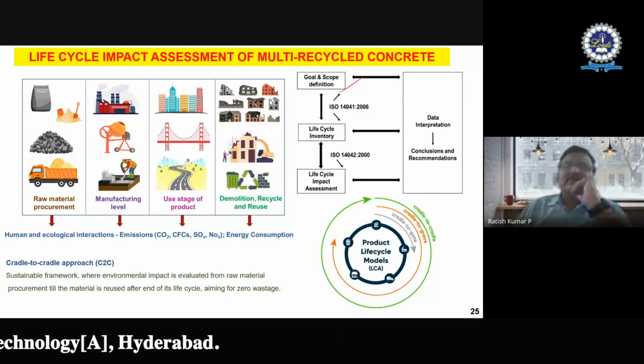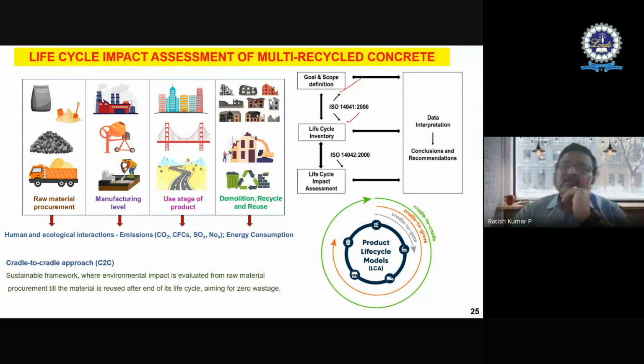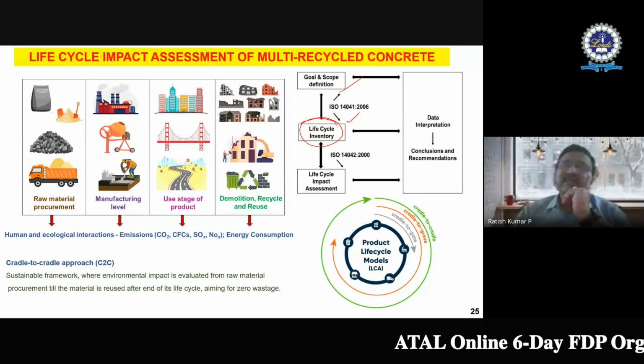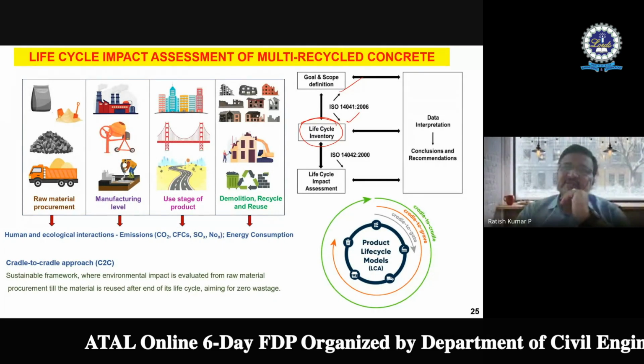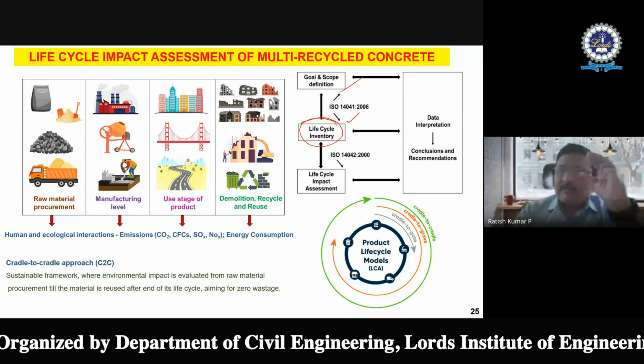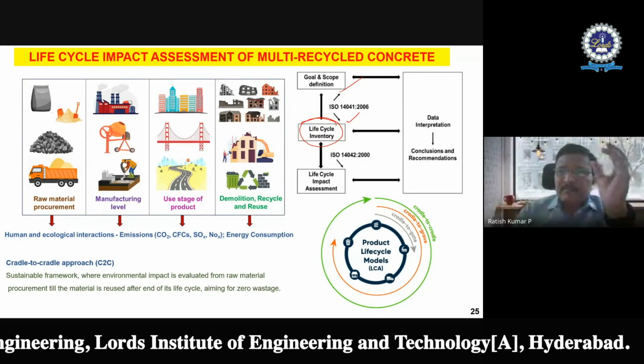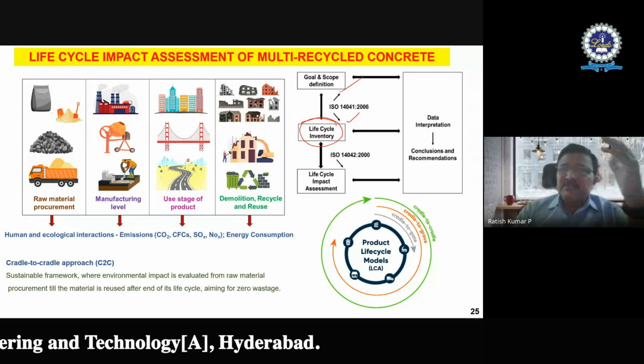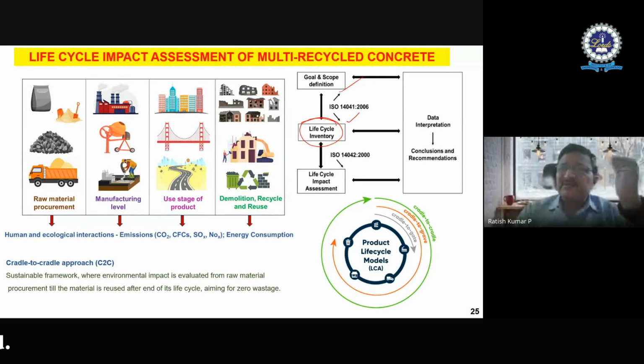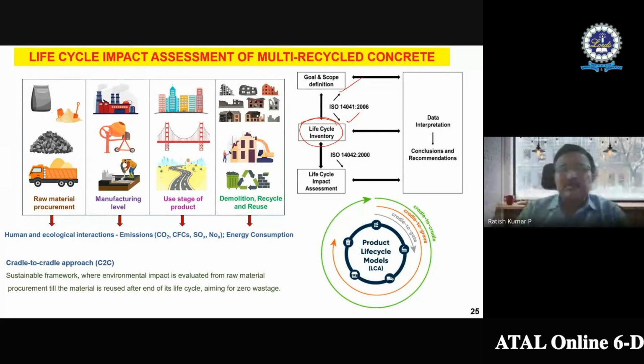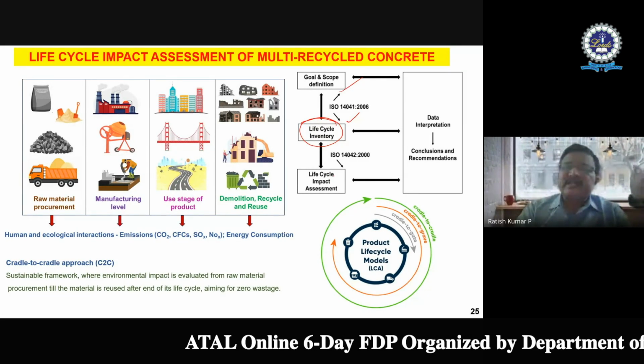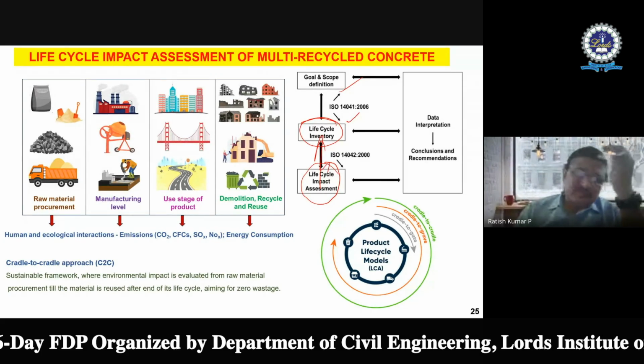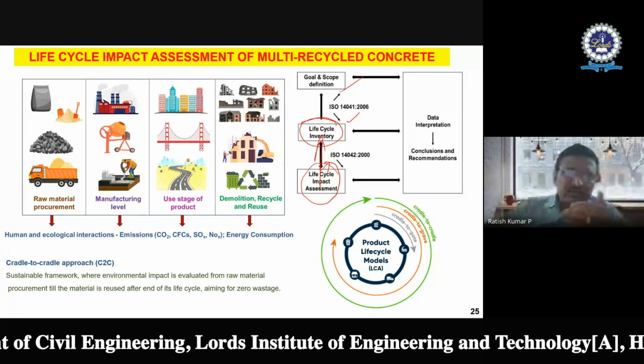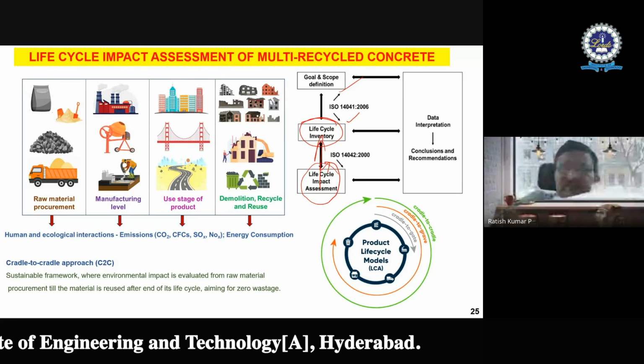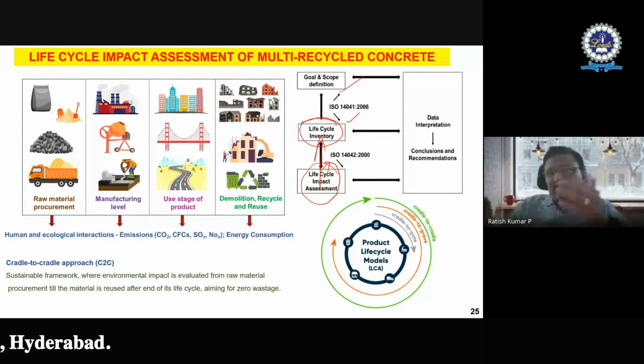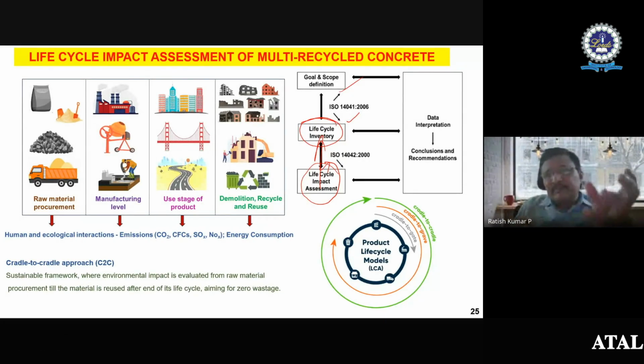And in this, we have something like a life cycle inventory, which is important. Unfortunately, not many people are working in this particular direction. This is a gray area. Somebody can actually go into this direction. If you really want to work on a new material, or if you want to go for binary, ternary, tertiary combinations of different materials, it's good that you try to establish a life cycle inventory of that material. Otherwise, we don't know whether it is doing good to the concrete or bad to the concrete. So that's one thing. And then you try to establish a life cycle impact assessment. You go up and down to check whether I can replace this material, I can increase the silica fume, decrease fly ash, increase metakaolin, decrease this one, add bioash, even if it is 2 to 5% of biochar, which is obtained from a pyrolysis process.